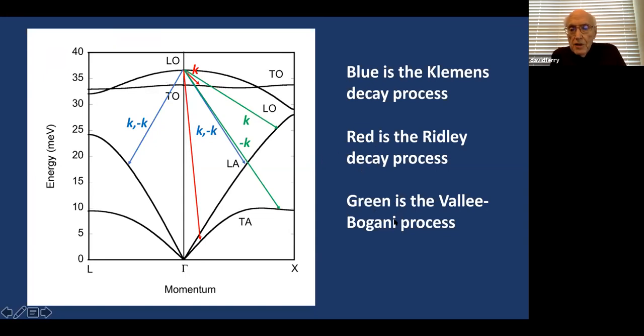And so then a Frenchman and an Italian working together, which is kind of a recipe for disaster, I think. But Vallée and Bogani, who have the green one, said I could decay into an LA and a TA mode with opposite momentums and still satisfy momentum. Well, this was not seen much. And we'll see in a minute that the red one actually just dominated the wurtzite crystals. Okay, so you have these various processes of decay. Now, people have thought about cutting off the Klemens processes by looking for materials where this LA peak here is less than half the LO peak. They want to do indium phosphide, but they haven't checked the data. It doesn't satisfy. I mean, indium phosphide still has the Klemens process. The only material I know of where you might cut off the Klemens process is indium nitride, and possibly gallium nitride too, but that doesn't mean you're going to cut off phonons.